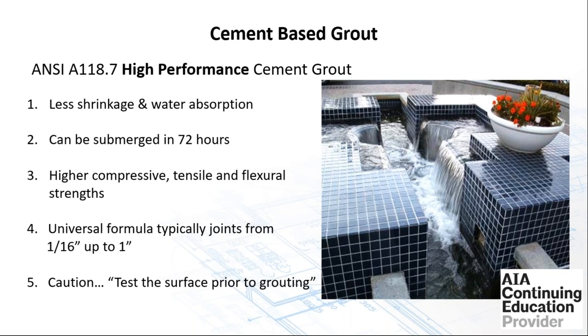few years back where we had a pool in a multi-million dollar condominium project in New York City. And obviously the tenants are paying to use their pool. We had a couple of tiles that came apart in the bottom of the pool, so obviously the downtime was a concern. The best installation for that application is using a fast setting mortar, which means you can come back and grout it in 3 hours. And then within 72 hours, using this 118.7 calcium aluminate, high performance, highly hydrated cement, it can be submerged. So in that particular installation, that was the best product to use.